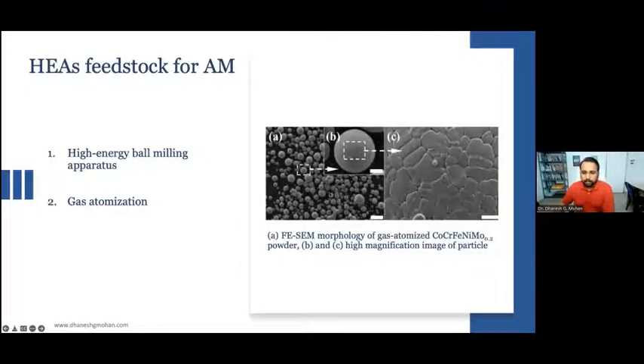In the same image, you can find that it's still not in spherical shape. Some debris is visible over here, and some of the material is not in spherical shape. So if you use this material for additive manufacturing, you never gain a better surface finish. And obviously, this debris and these non-uniform materials cause defects. That means cracks, maybe some porosities. All these defects may happen.